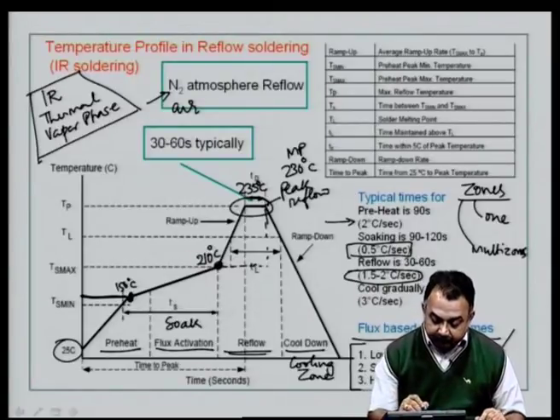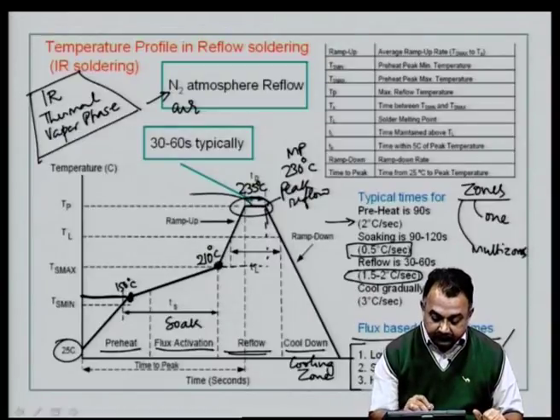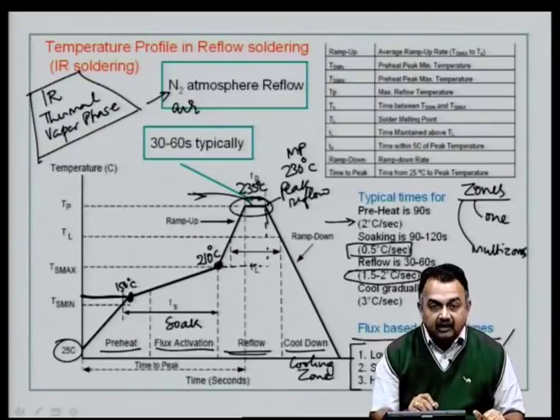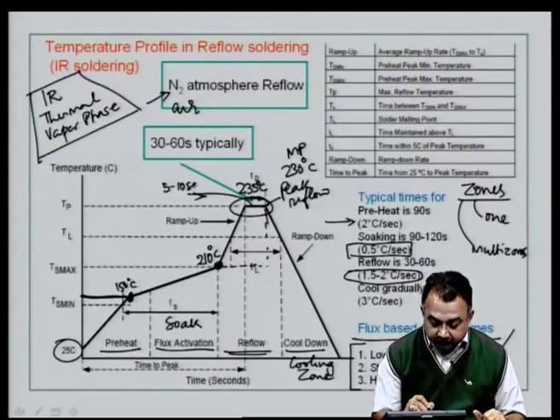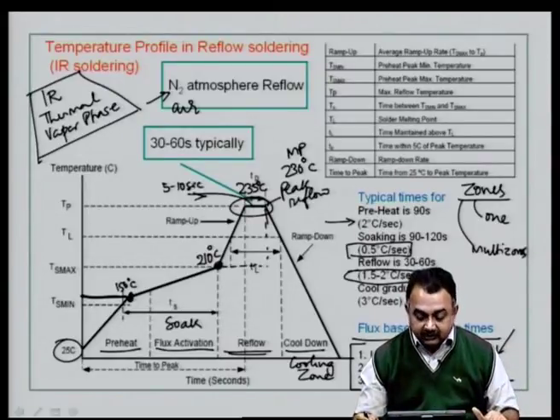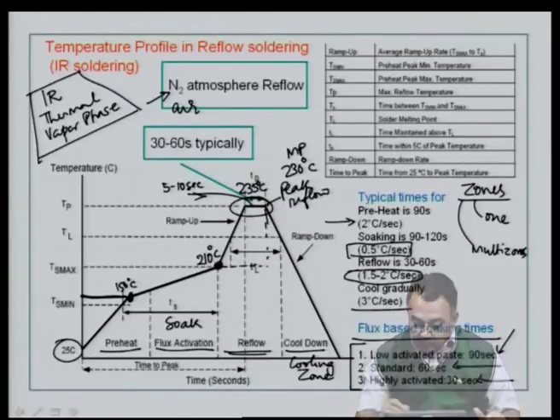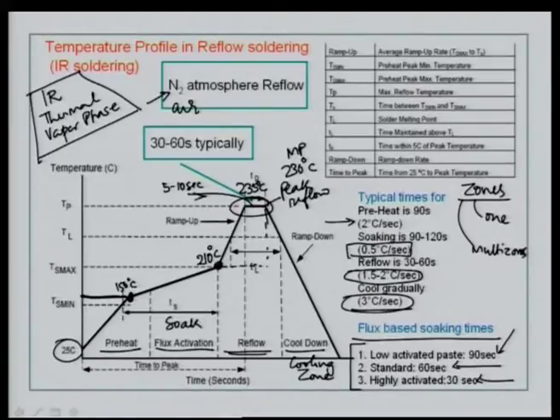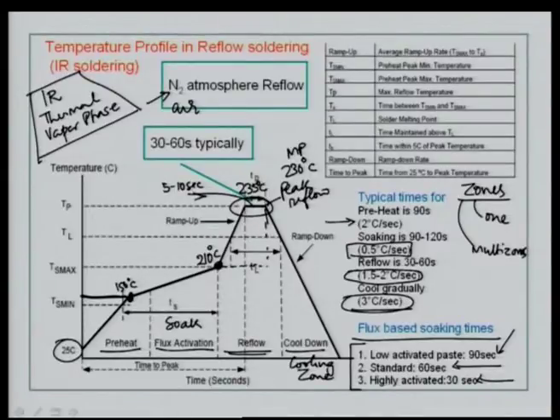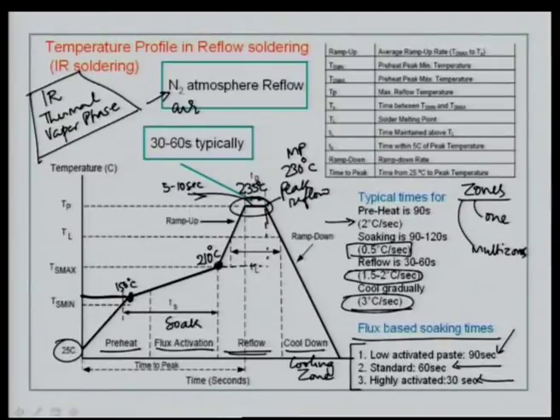From 210°C to 235°C will be the reflow zone, which should be fairly fast — 1.5 to 2°C per second. You can have a very small residence time at peak reflow of about 5–10 seconds, sometimes larger, and then start the cooling zone. Cooling has to be gradual — from 235°C to room temperature should be done at about 3–4°C per second. The entire process from the 4 stages — preheat, flux activation, reflow, and cooling — should typically end in about 5–6 minutes.